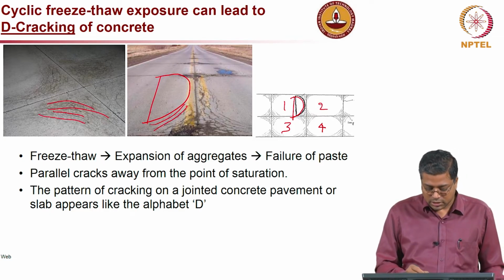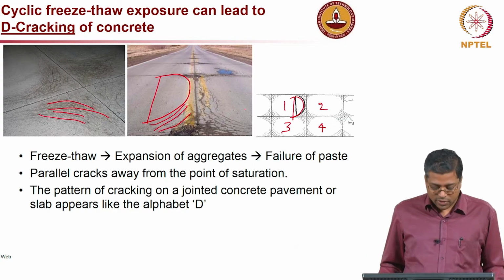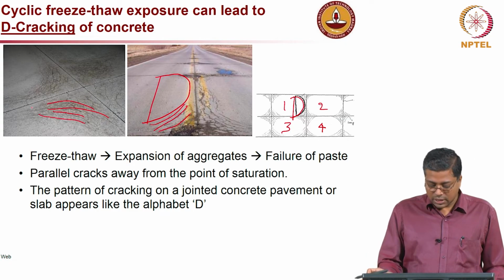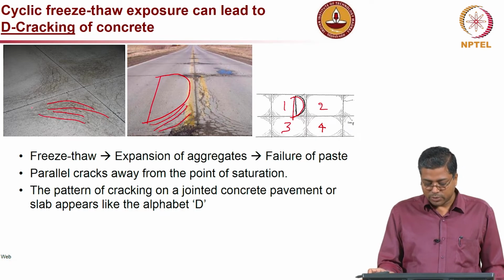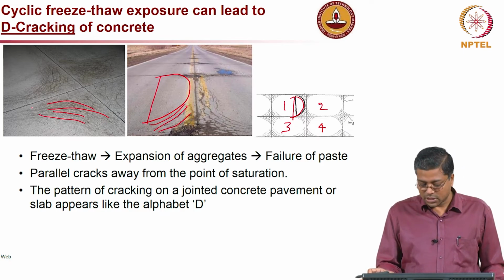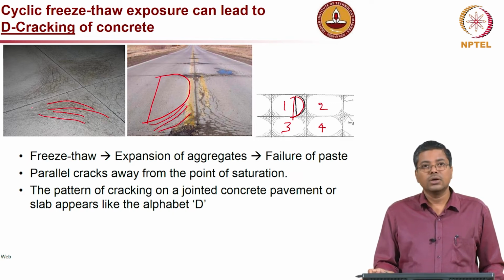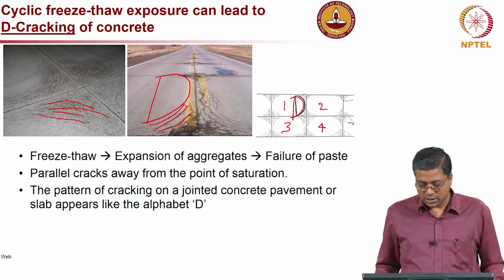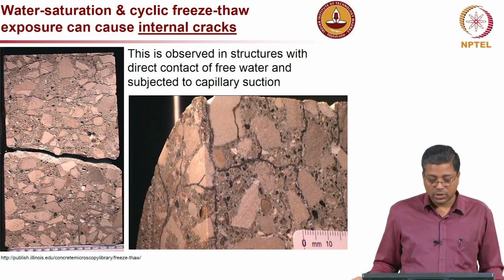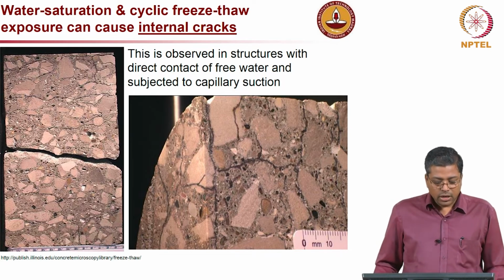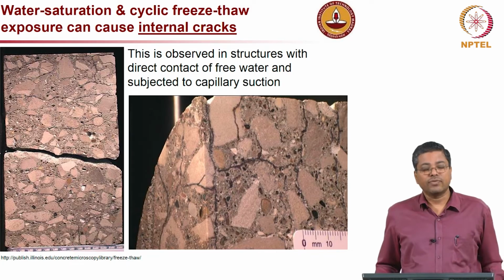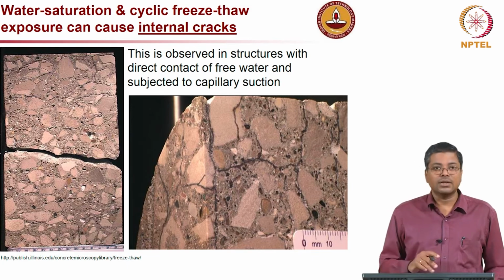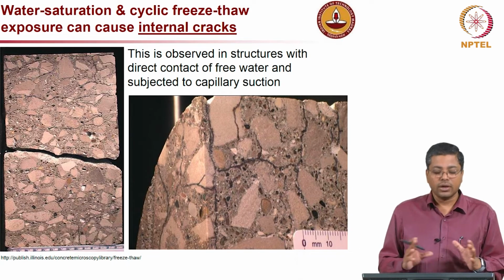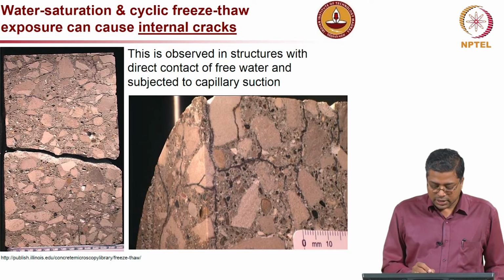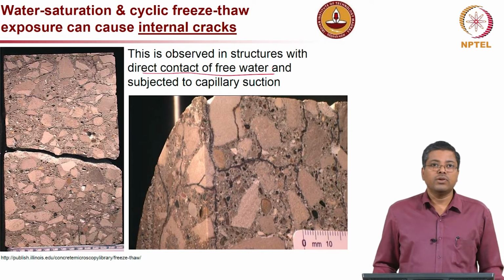So, here also you can see parallel cracks, they are actually away from the joint, which is the saturation point. So, this cracking is something which is widely observed especially on exterior concrete elements such as roads, which are directly exposed to the environment. Now, water saturation and cyclic freeze-thaw exposure can also cause internal cracking, especially in cases where the concrete is in direct contact with free water.